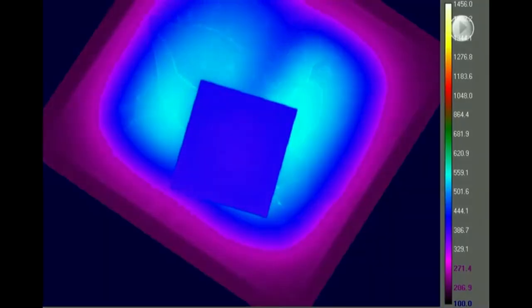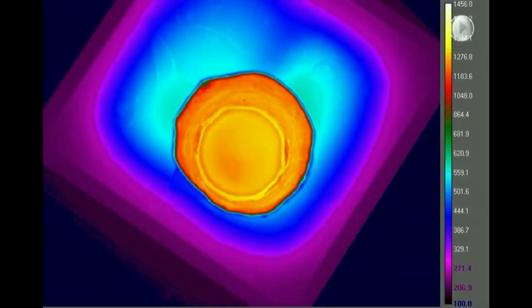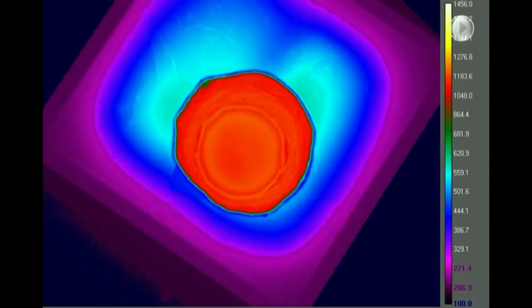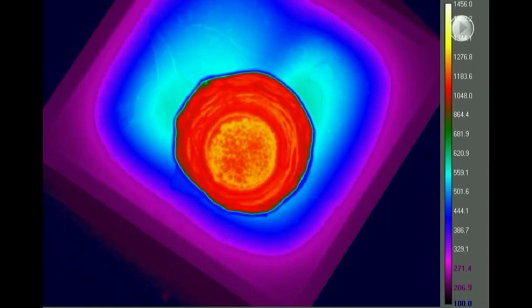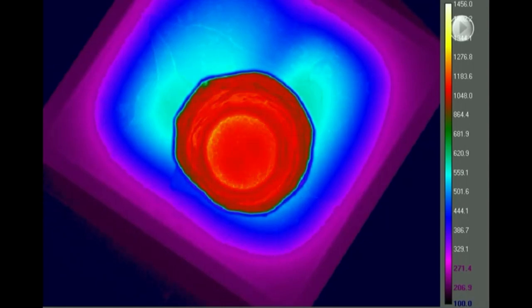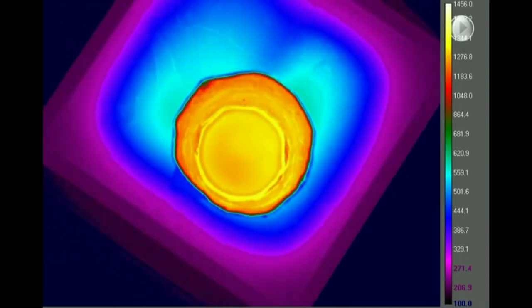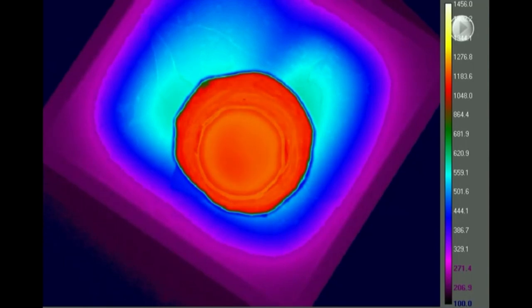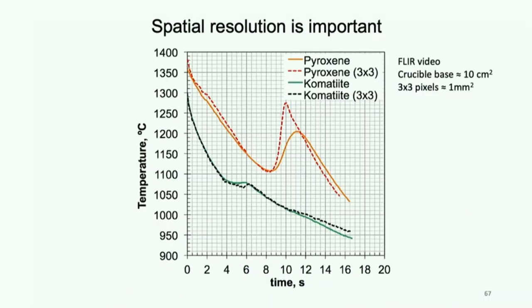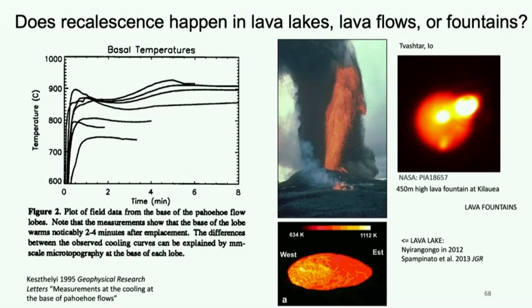All right, I'm just going to show you this. This is our lava in a crucible. It's cooling, it's about to crystallize, and off it goes. This is coded for temperature. This is obviously not a visible image. This is just color coded with the FLIR camera. So what's happening there? Why were the crystals hotter than the liquid? It's because the crystals are releasing latent heat. And so actually what happens is we can make lava spontaneously heat up by about 200 degrees by cooling it at just the right rate and getting it to crystallize really quickly, which is of possible relevance to Io.